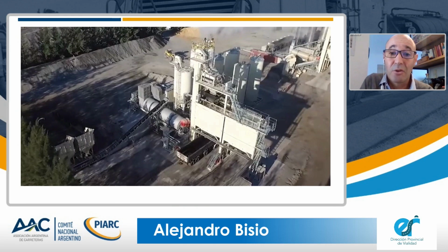Here you can see the continuous flow plant. On the left, you can see the feeding system, two hoppers for each of the different RAP fractions, and a conveyor belt that sends the material to the drying drum with no contact with the flame, and then we have the mixture of the RAP with the virgin aggregate and the filler. Then the material is sent to the upper part where the mixture is made and the virgin asphalt component is added. The other is a batch plant where the RAP was added to the mixture and entered at atmospheric temperature.